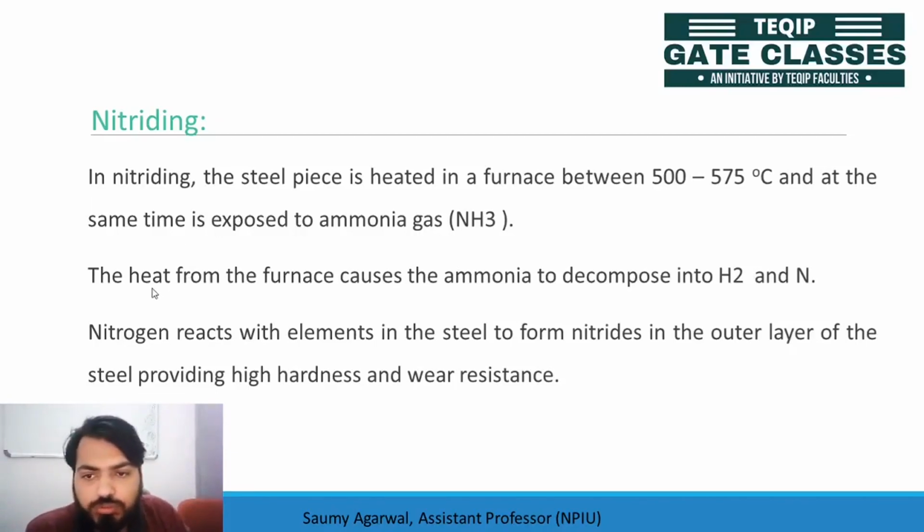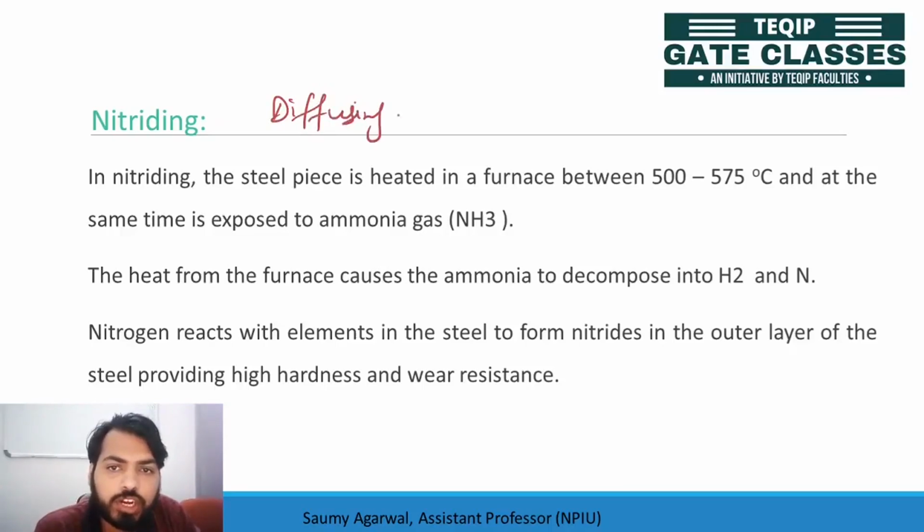Okay, so due to this heating, what will happen? The ammonia will decompose into hydrogen and nitrogen. Okay, and this nitrogen will react with the elements to form nitrides in the outer layer of the steel, providing high hardness and wear resistance. Okay, so in the nitriding process, you are diffusing the nitrogen.